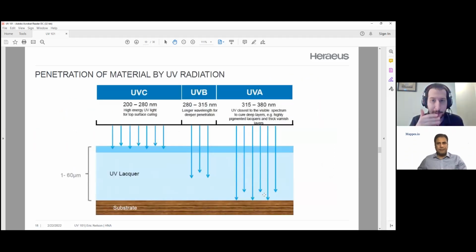Yep. So how does UV penetrate a material? Like I mentioned, the wavelengths do play a role here. And typically, we choose a lamp and we choose a bulb based on the wavelengths that are needed for different processes. So if you have a very thick process or something that's very pigmented or difficult for the UV to penetrate, you're going to want the long wavelength UV energy, the UVA energy. And that's because when you think about a wave or a particle moving through the air in a wave, it's a very long, wide particle for the UVA energy. This means that it's able to penetrate very deep into a material. Okay. Lower wavelength UVC energy has very, very sharp, small peaks. It's almost going to contact as soon as it hits the surface material, it's going to be absorbed. I see. So it's not able to get very deep into the material.